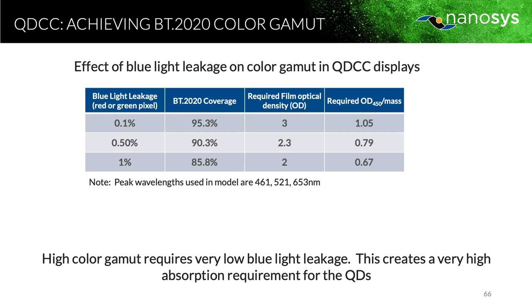So this is really important when considering gamut coverage. You need high absorption. So obviously we'd like to be somewhere up here. So what are the requirements generated by desiring these levels of gamut coverage? Well, you can see that the required film optical density is between 2 and 3 units of absorption. And what's most interesting then, and we'll take this forward, is this requirement. Now, this is a unit you've probably never seen before: optical density at 450 divided by the mass. This is a property of the quantum dot, how much light it can absorb on a specific mass basis. I don't expect you to remember this, but just note that the numbers are between 0.7 and 1, approximately. So that's what we would desire.